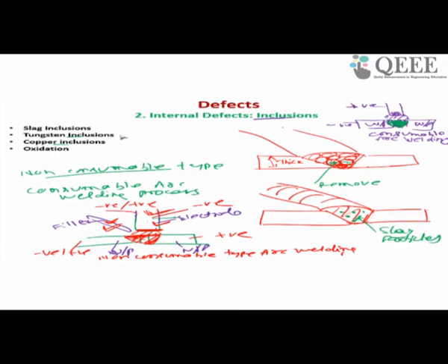That's why you use either tungsten or copper as the electrode material. Even though we use tungsten or copper, some level of heat is also developed at the interface, and it is possible that some fragmentation of tungsten or copper from the electrode may deposit in the weld pool. This is called inclusion.